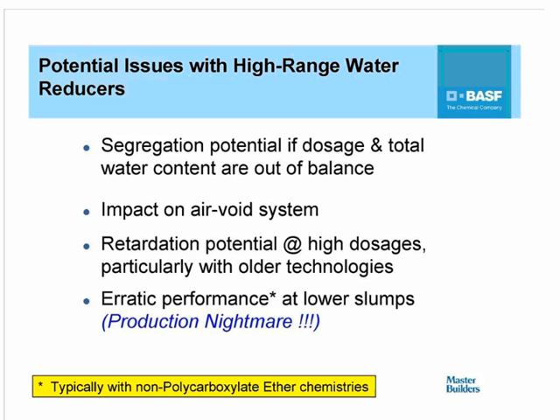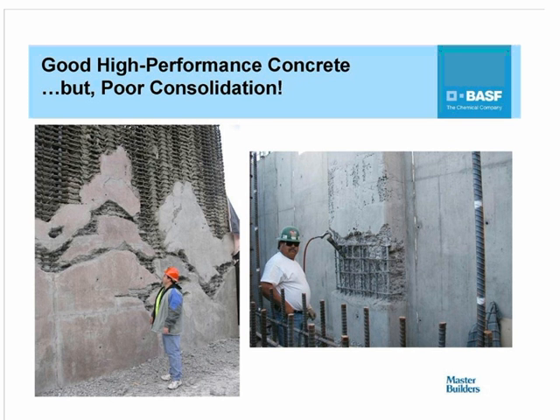Years ago, there were some state agencies that would permit the use of high-range water reducers, but then limit the slump to no more than 5 inches. And that created a lot of havoc or problems with respect to the slumps and the performance. These days, I think most agencies understand that these materials have to be used at much higher dosage, much higher slump levels, and are open to that.